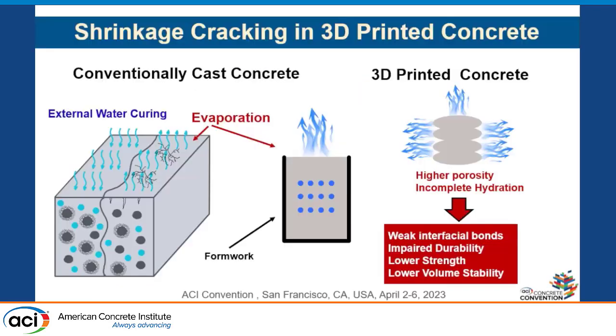We all know one of the major problems with 3D printing: evaporation and drying, which can cause volume stability issues. For conventionally cast concrete, we have formwork, and the width of the sample is not that high, so evaporation causes a serious problem mainly with higher water to binder ratios. But when we have a lower water to binder ratio and a larger drying surface, definitely we're going to have more evaporation, and we need to think about that.